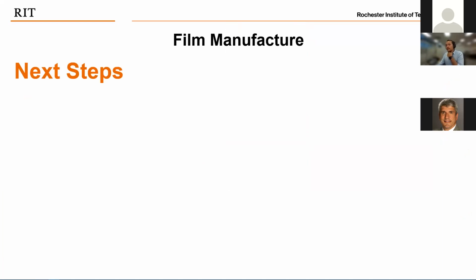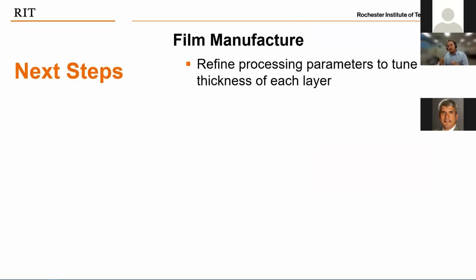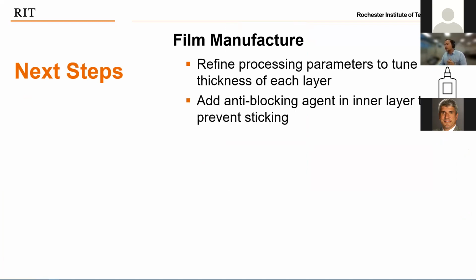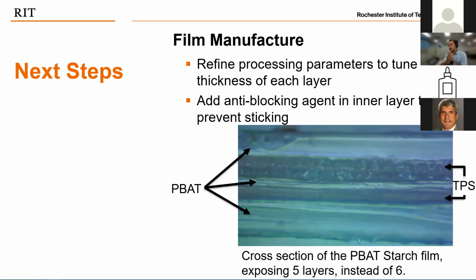Well, for the film manufacturer, we have to tune and refine the process to find the thicknesses of each layer we want, and to understand a little bit more of the complexities we find there. The way a blown film line works is that the plastic comes like this, and then it roller casts, and the inner layers touch themselves, and we were finding that they're sticking to each other. So the PBAT is sticking to itself and fusing into only one layer. And so this explains why we're having such a thickness.